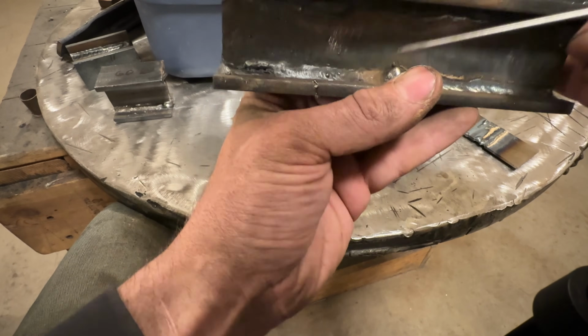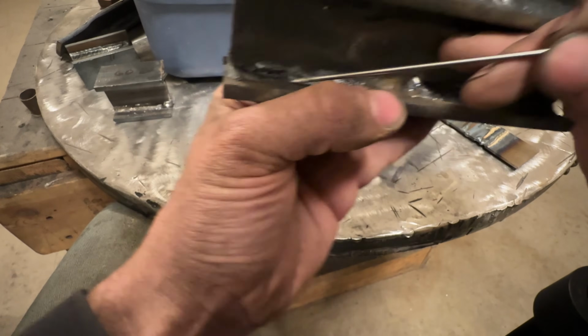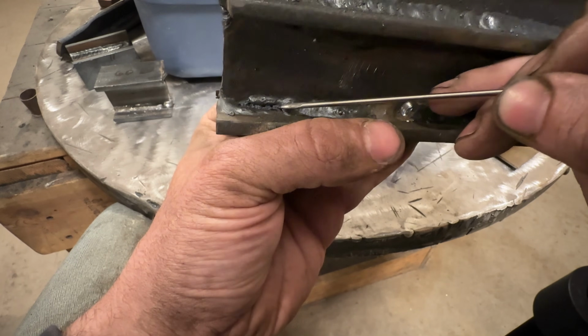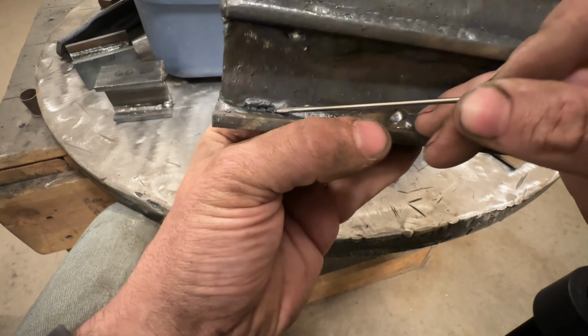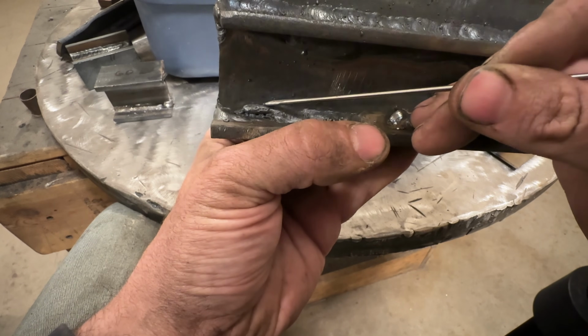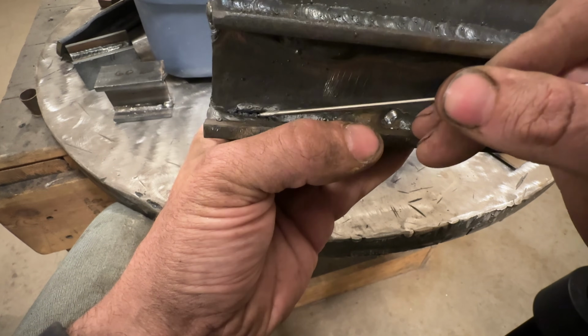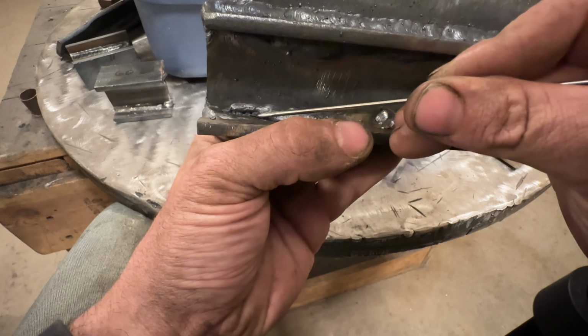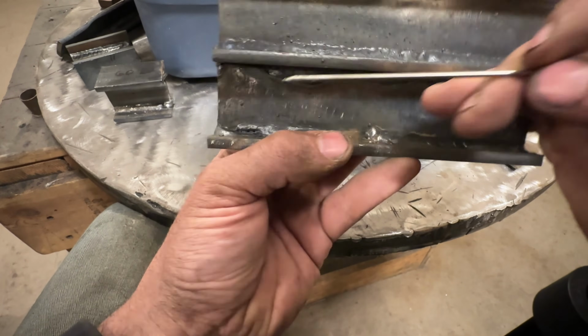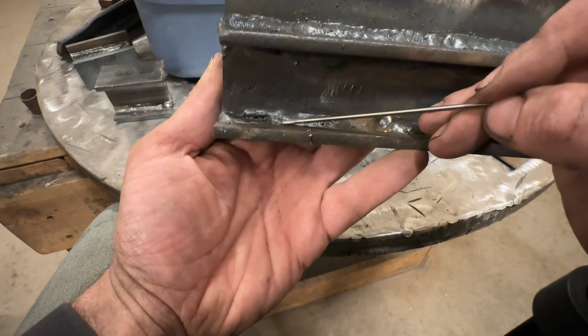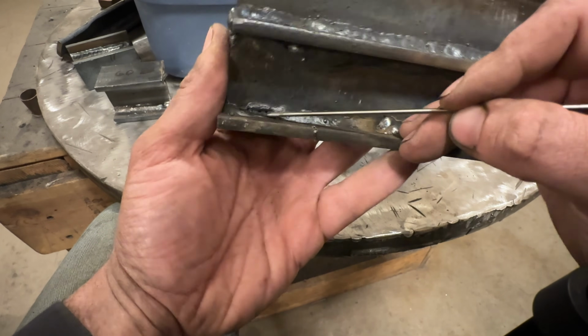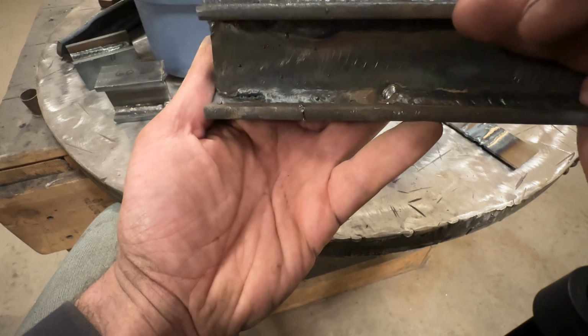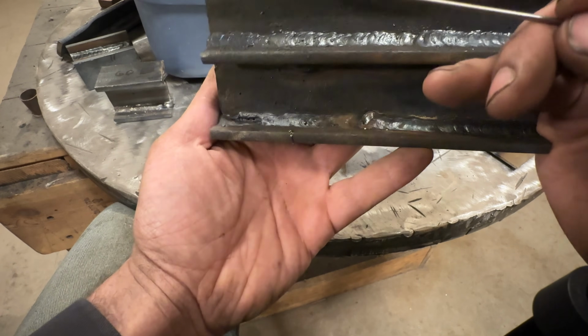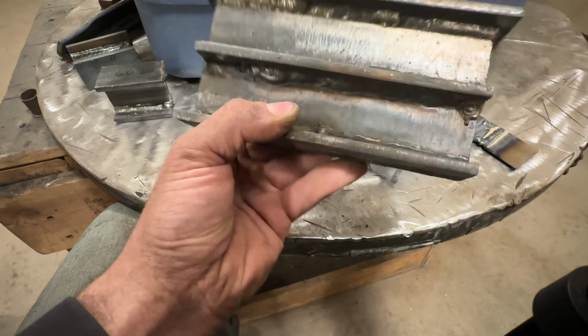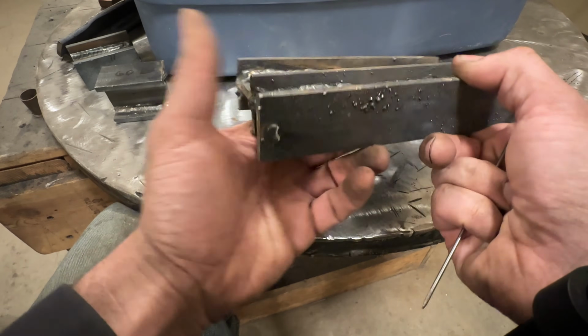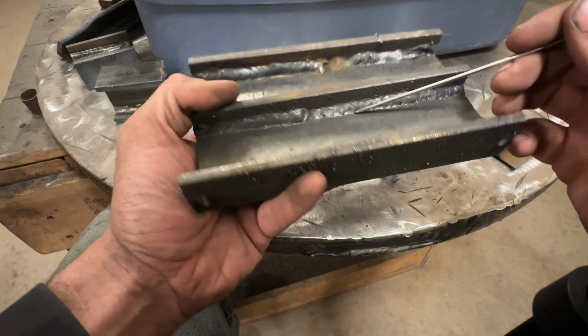We don't want that. And here's the best I've seen so far for slag inclusion. So if you see here, the weld just deposited down here and over and completely just went around this. That's very common with 6013 rods, or if you run a rod at the wrong angle or too low of amperage. So that's, again, defect, no good. Now this, other than undercut, that looks good.